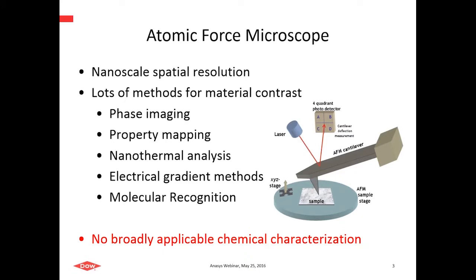Now, in contrast, atomic force microscopy readily gives us nanoscale resolution. We have a well-controlled force of a nanometer-sized tip in contact with the surface that we're studying. There are lots of methods to see material contrast in many modes of AFM operation. Several are listed here that give us mechanically mediated mapping, or adhesive, electrical, and thermal property analysis, even those that Craig alluded to earlier from Anasys.